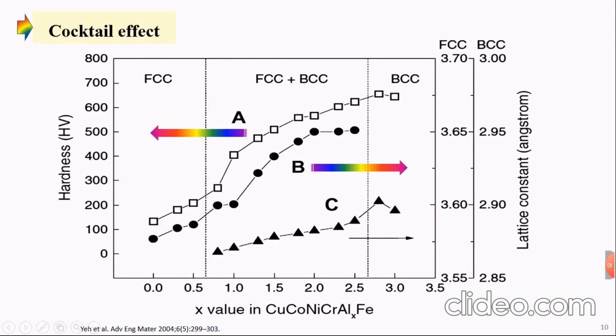What does the cocktail effect mean? In regular alloys, if your alloy is an aluminum alloy, you expect that it will be soft and deformable, and so on. If you have a titanium alloy, you will expect it will be hard, with high strength, corrosion resistance, and so on. In high entropy alloys, you cannot determine exactly the properties because, for example, here, this is the relationship between hardness and the x value of aluminum in this alloy. So we have a copper, cobalt, nickel, chromium, iron alloy, and we add aluminum with small additives. If we see here, the alloy up to 0.5 has an FCC structure. When we add more aluminum, it became FCC plus BCC solid solutions. If we add further, we go to BCC. And unexpectedly, the hardness increased with adding aluminum, although aluminum is a soft element.